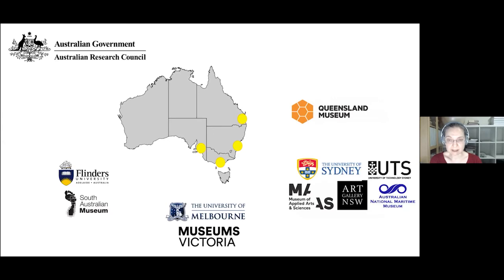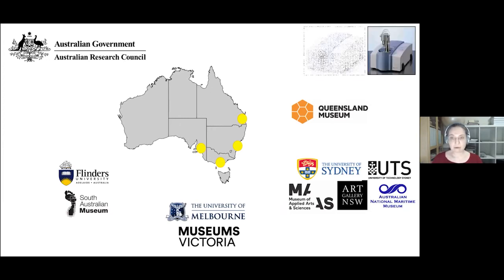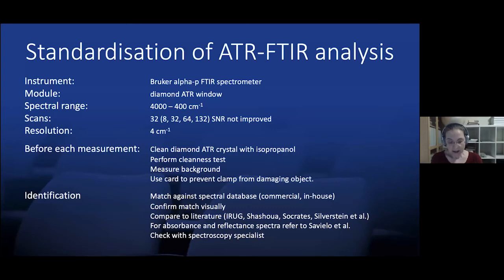However, before progressing with making measurements, we were aware of the need to be able to compare data between the different project partners, and that the data will, in the long run, become accessible to the conservation profession and future researchers. So we had to do preparation work to optimise our processes before we rushed in and surveyed collections. So our standard FTIR data collection process, which I have here for the ATR module, is where we determined that the signal to noise ratio is optimized after about 32 co-added scans, and there was no point doing any more.